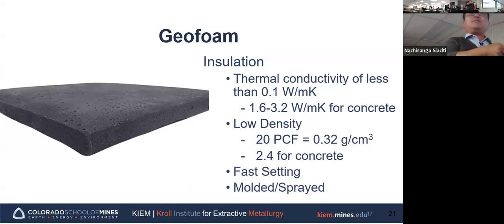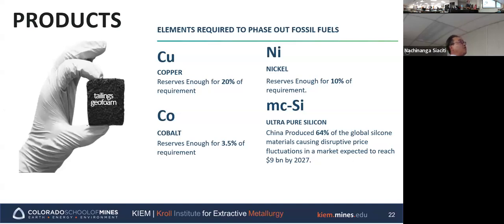The thermal conductivity is pretty low. Typical concrete is about 1.6 to 3.2 watts per meter Kelvin, but the geofoam is only 0.1 watts per meter Kelvin. And as we can guess, the density is pretty low. It's really light. Concrete and gangue minerals are 2.4, 2.3 grams per cubic centimeter, but this one is only 0.32. And the setting speed is very fast. It could be molded like this, and it could be sprayed. One of my students is still working on making this. We can put it in a mold and easily make different shapes and forms.